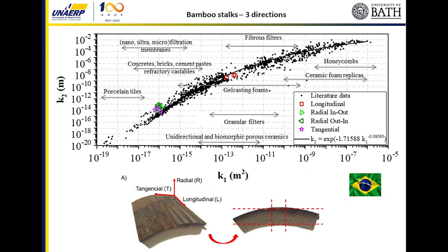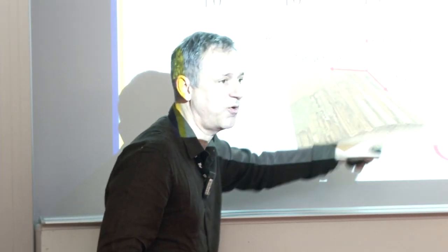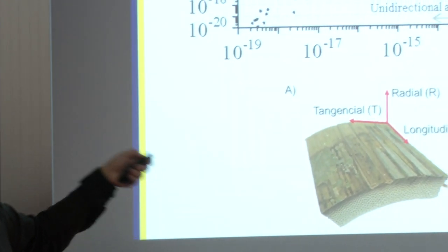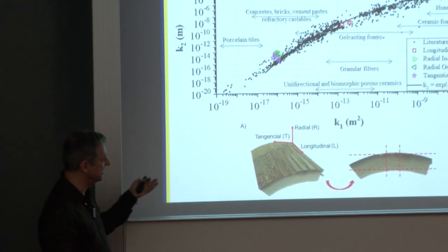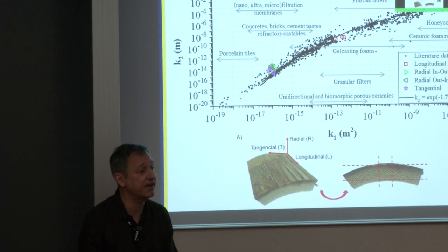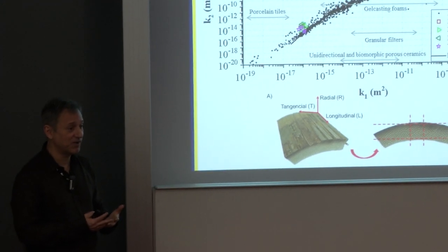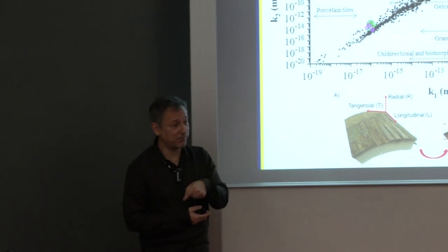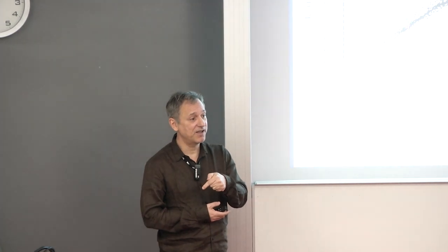For the bamboo, bamboo is a very interesting material because you have the permeability like adobe brick. You have the three directions. And for example, for bamboo, you have one direction here. If you go in the longitudinal way, you have almost four orders of magnitude higher the permeability. So what's the point for this material? For example, if you want to impregnate a resin inside the bamboo, you can predict the time to impregnate. To predict the time for impregnation, you need to know the permeability.